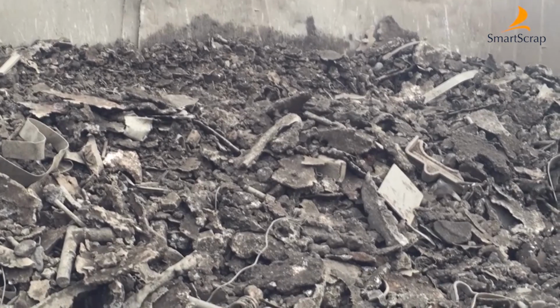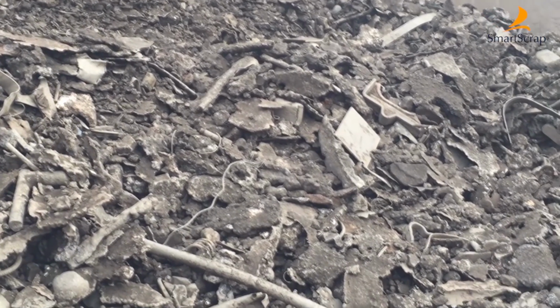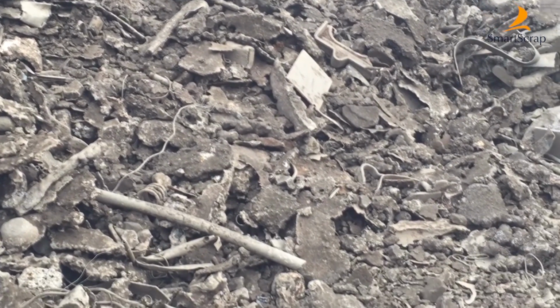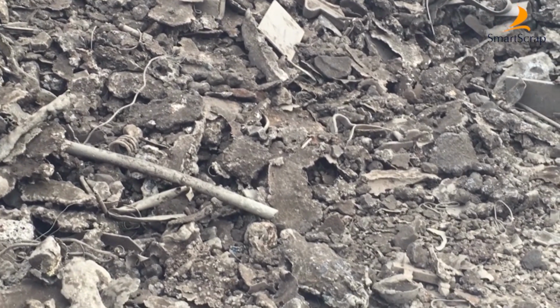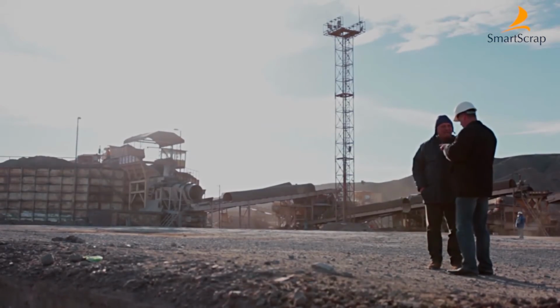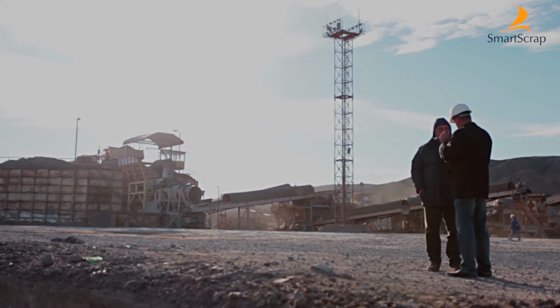The cleaning system that was installed during the modernization of the unit allowed achieving rather high levels of metallic iron content, which in its turn has allowed metallurgists to use up to 70% of scrap as part of the batch during melting.